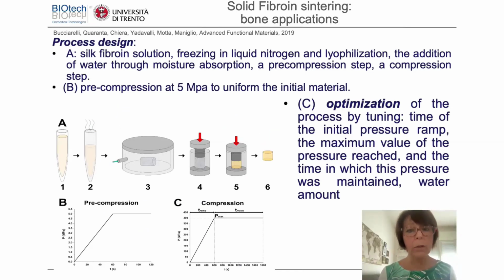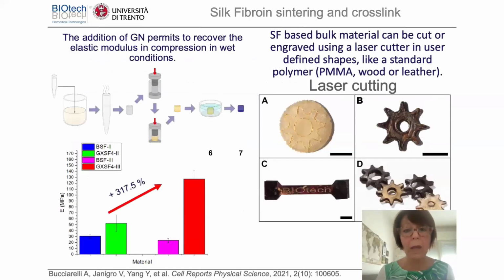Moving then to the processing method, we are optimizing our method, again considering the possibility to reduce the time, the temperature, and the cost. This is just an example: a sintering of a solid fibroin designed by Professor Maniglio and Dr. Bucciarelli. They start from freeze-dried fibroin isolated from waste, and the powder is treated in compression in the presence of water at a very mild temperature, very close to room temperature. With this system, solid materials are obtained that can be cut by laser, obtaining different shapes.